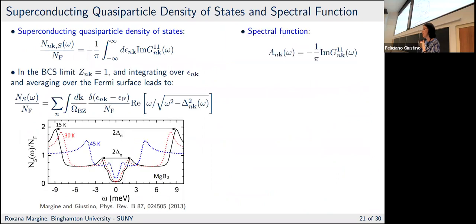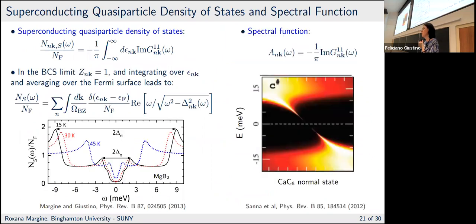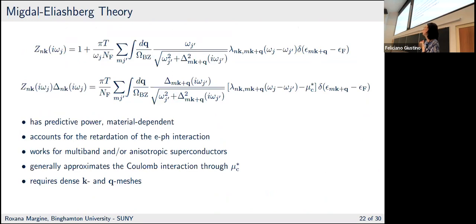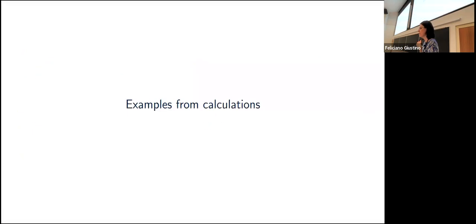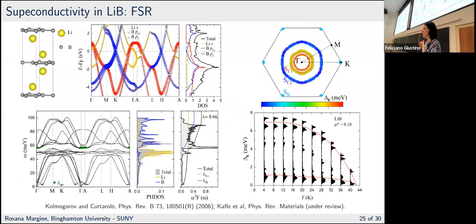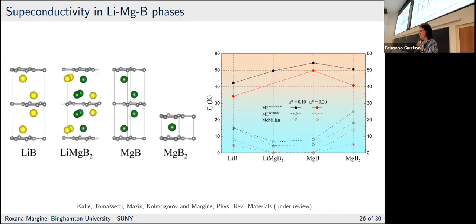Allen-Dynes basically gives the same result as if you were to solve the isotropic equations. And the reason for that is, if you do an isotropic calculation, you will get an average gap, which is kind of in between these two. And if you just solve this, you will get roughly half of the TC. As you can see in this plot, the isotropic calculations are quite close to McMillan or Allen-Dynes. It's basically because you are more or less averaging the gap.